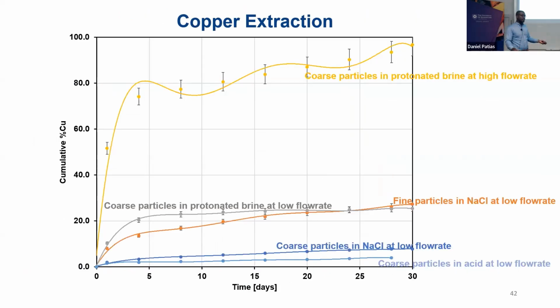What does this mean for copper extraction? I guess that's where we're driving at. So if you plot a graph of copper extraction over time, for coarse materials in that protonated brine at high flow rates, we get high recovery for copper, nearly 90% or more. I should say that in all instances, for both high and low flow rate in the protonated brine, for coarse material we're getting much more copper compared to in sodium chloride rich brine and in acid.